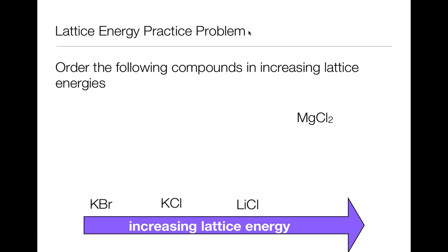With a little research, we can find out that magnesium 2+ and Li+ actually have almost the exact same ionic radius. Lithium is about 90 picometers, while magnesium 2+ is 86 picometers. With this information, we can see that MgCl2 will have a greater lattice energy because it has roughly the same distance between the center of the ions as lithium chloride does, but magnesium has a 2+ charge. So therefore, magnesium chloride is going to have a larger lattice energy than lithium chloride. And by process of elimination, essentially, we've now ordered all 4 of the compounds. So this is going to end our lecture on ionic bonding, the Born-Haber cycles, and the lattice energy.